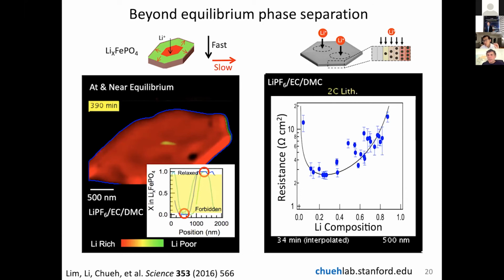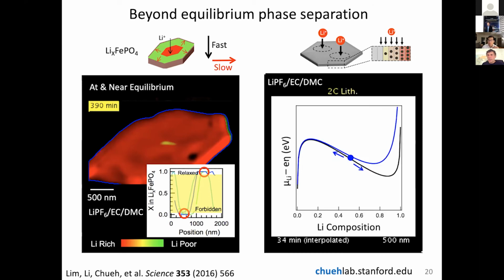This is a measurement that we did using X-ray microscopy, where we measure the interfacial resistance, so how much driving force is needed to put lithium into the particle. And this resistance is actually highly non-monotonic. It has the lowest value at about quarter filling, which means when you have about a quarter of the lithium sites occupied, it's easiest to put lithium into the system. So what is the implication on the equilibrium property of the material? Well, the black line here is the open circuit potential if the system doesn't phase separate. So you have a non-monotonic chemical potential. This is classical textbook. This is what will lead to a phase separation.